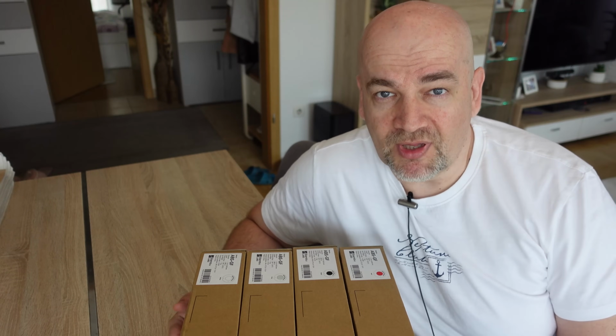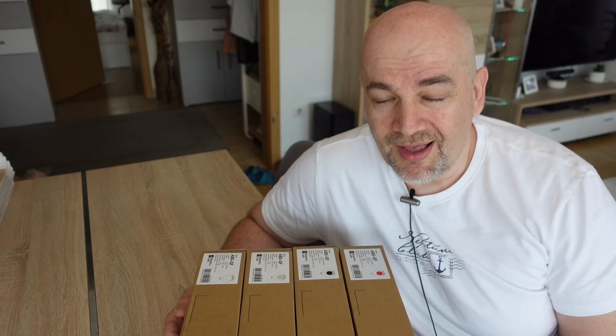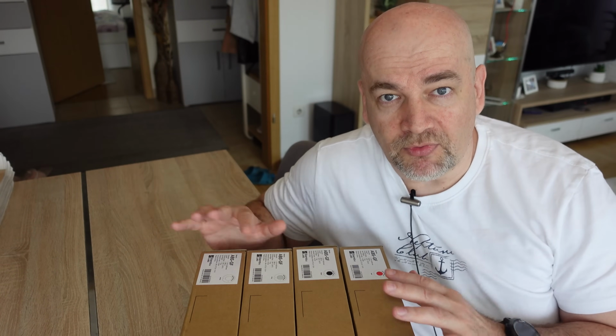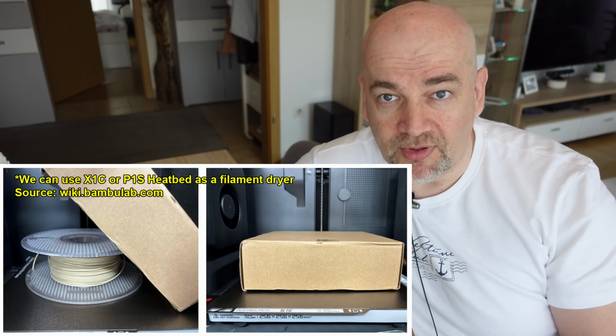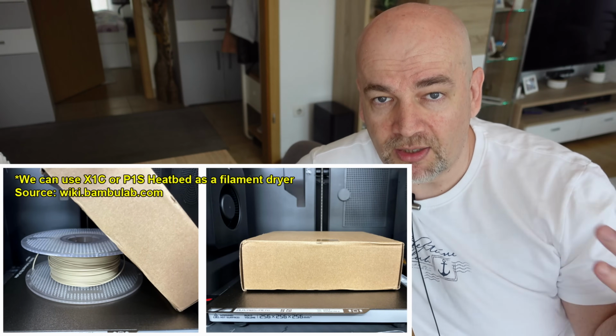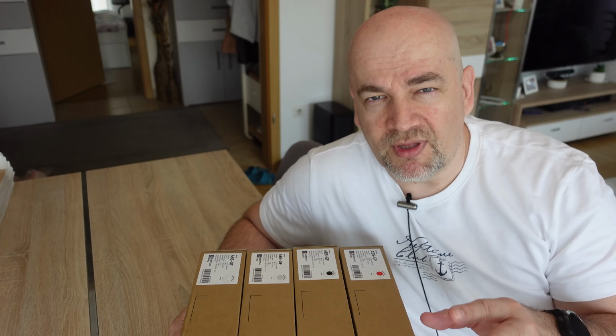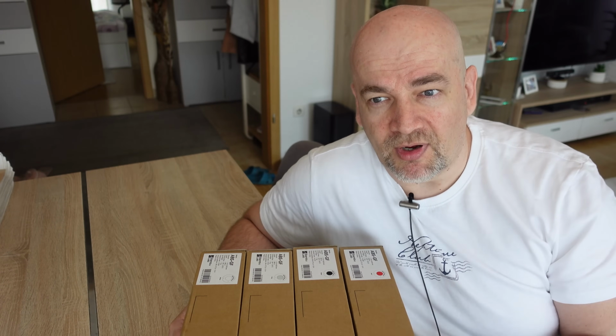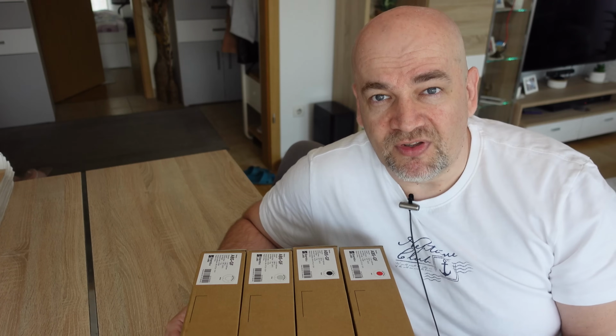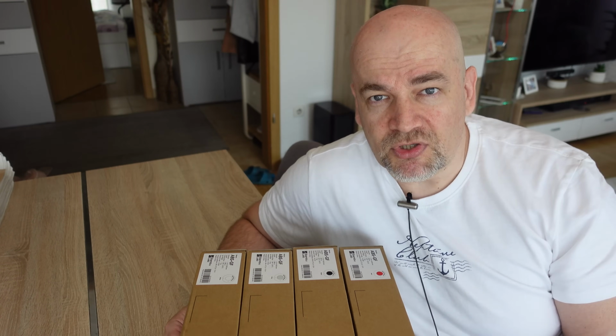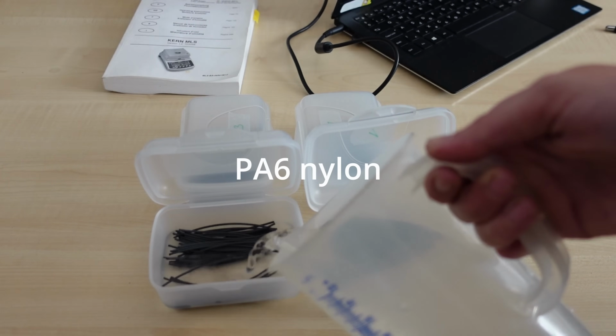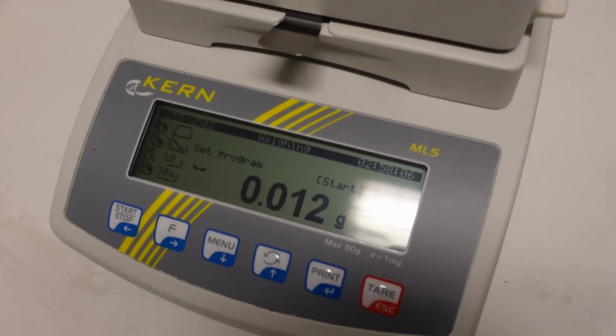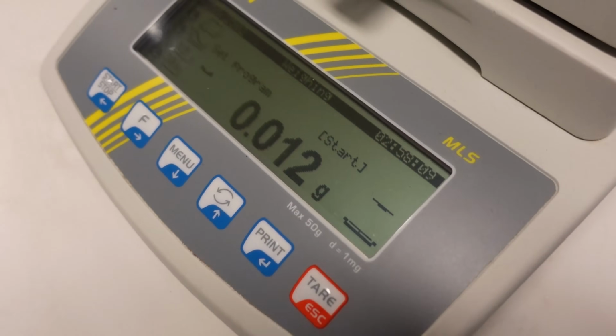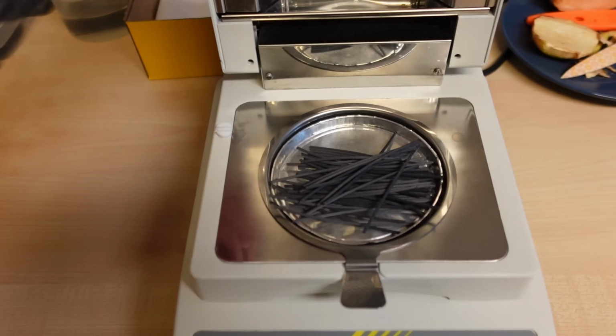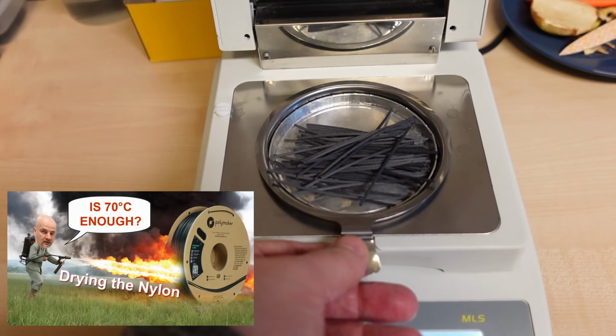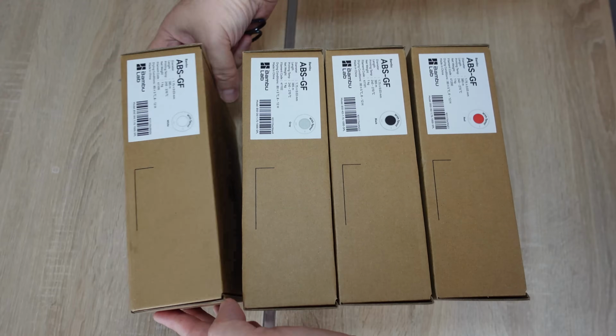I'm not sure if Bambu Lab knows that we don't have this kind of filament dryer on the market. I will not dry them, I will print out of the box, but maybe Bambu Lab should create some filament dryer which is able to dry the filament at high temperatures too. Soon I will have that comparison video of 6 filament dryers, but there the max temperature is 70 degrees Celsius. And we have some research at my university department, and drying of nylon, for example, at 70 degrees Celsius is possible, but it would be significantly faster at 80 or 90 degrees Celsius. More about that in a separate video.